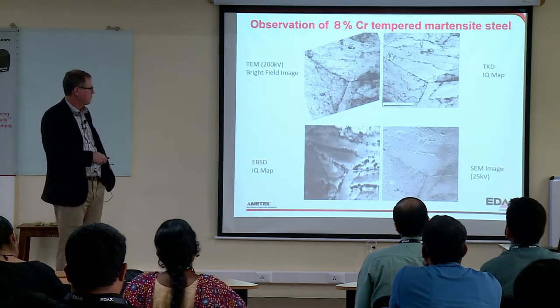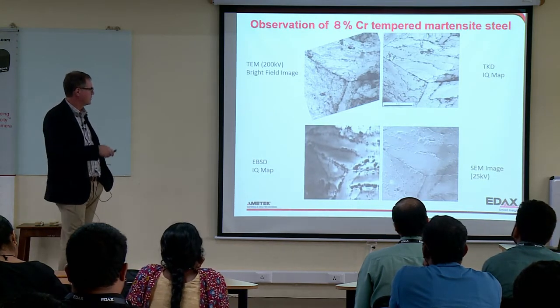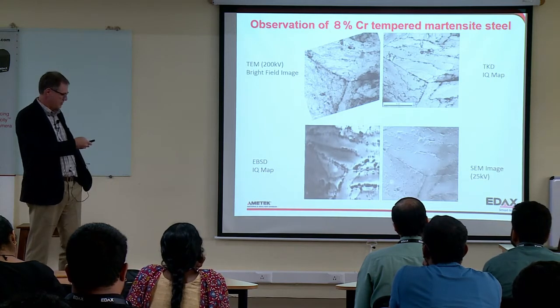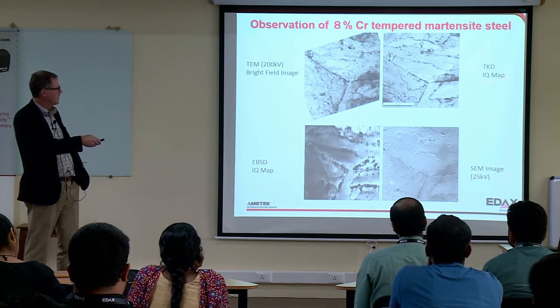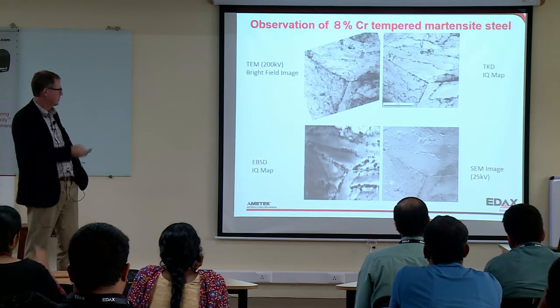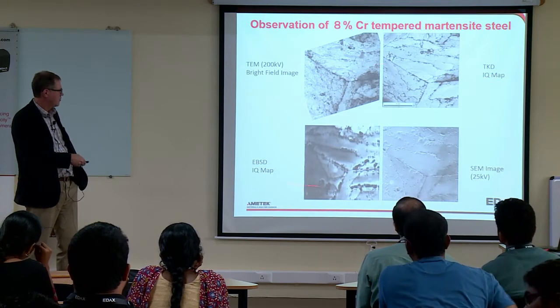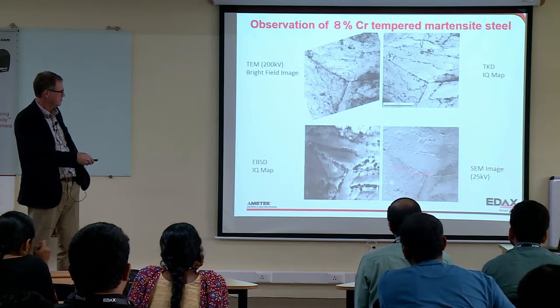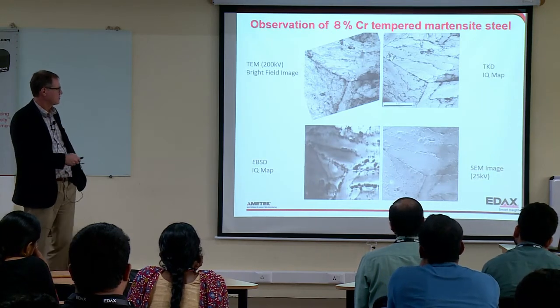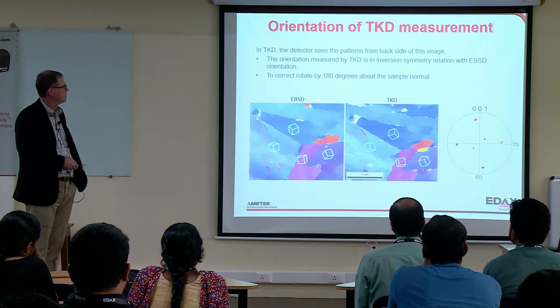This is just an example from Suzuki-san and the sample that he had. So this is a TEM bright field image, a TKD IQ map. You can see the similarities. An EBSD IQ map and an SEM image. And it's somewhat similar there. So it's a nice sample because you're able to do it both ways.